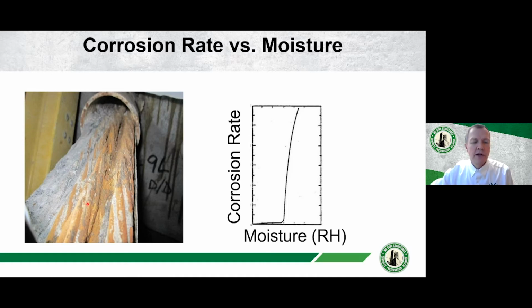And these exposed steel strands are going to be exposed to potential for corrosion, and the behavior of those steel strands with regard to corrosion is going to behave something like what is shown on this graph on the right, in that the corrosion rate is going to be really low if there's little moisture there, and then it's going to increase, and then once it starts to go, it's going to go up very, very high. And for a standard temperature kind of condition, you'll get a single curve like this. If you have multiple temperature situations, then you're going to have multiple curves, but the idea of showing you this at this point is just to give you the idea.